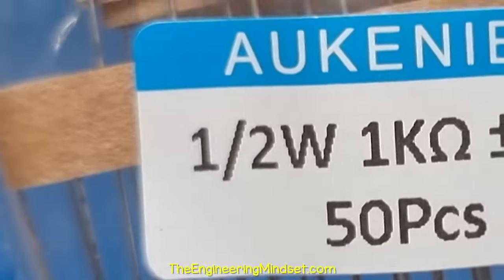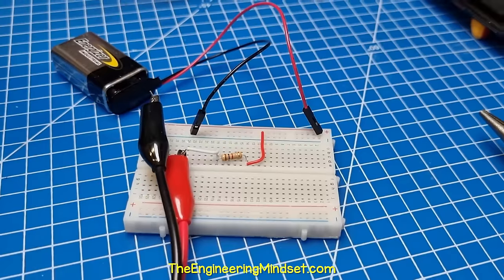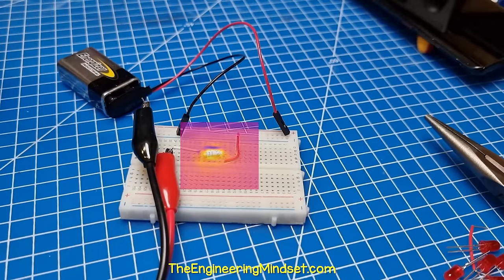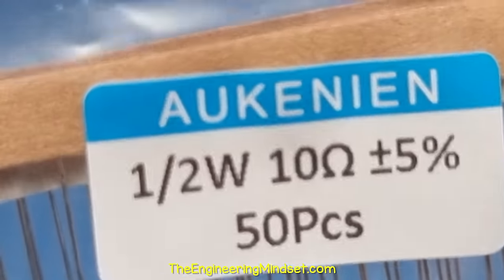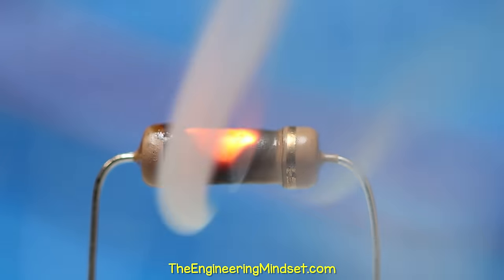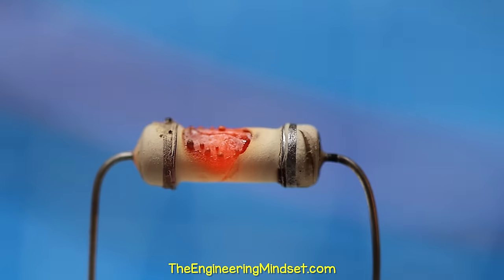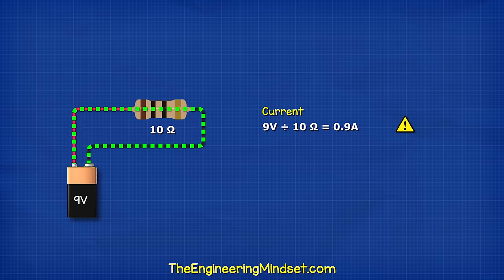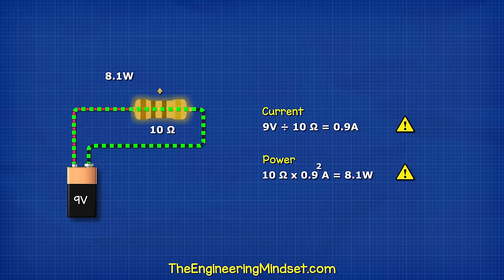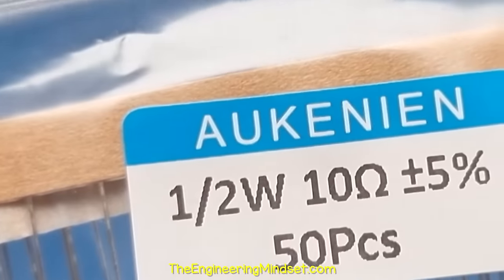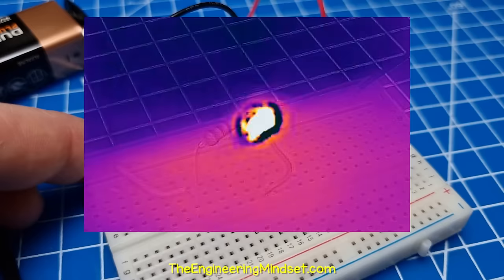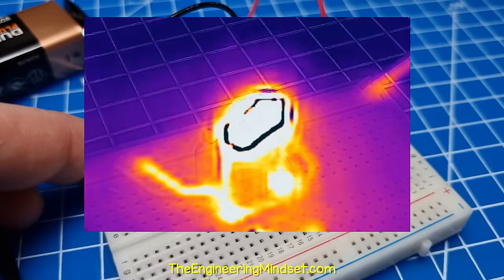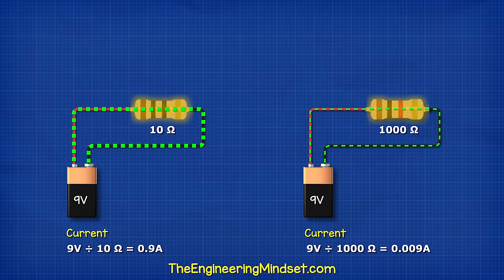As this is a 0.5 watt resistor, it will work fine and generate a little heat. But if we connect a 10 ohm resistor, it will catch fire. That's because the current is now around 0.9 amps. And so the power is around 8 watts. This is only rated for 0.5 watts, so it rapidly overheats and catches fire. So we can see that the higher the resistance, the lower the current will be.